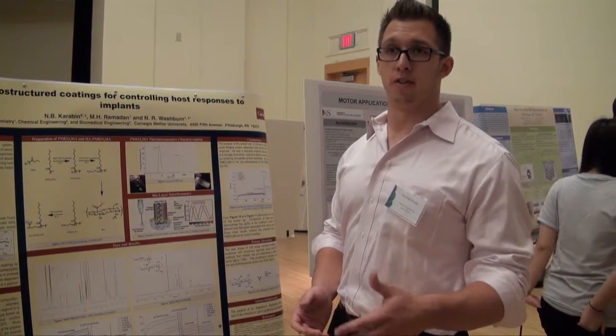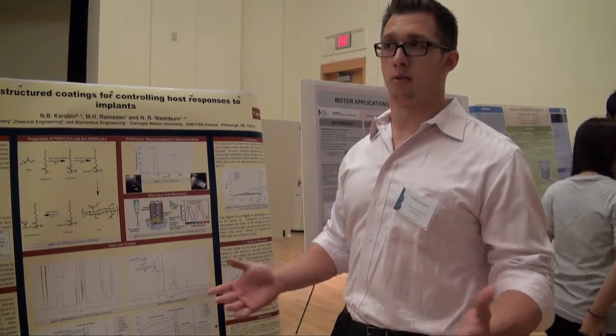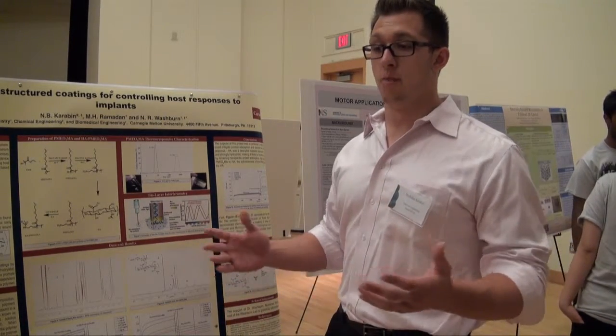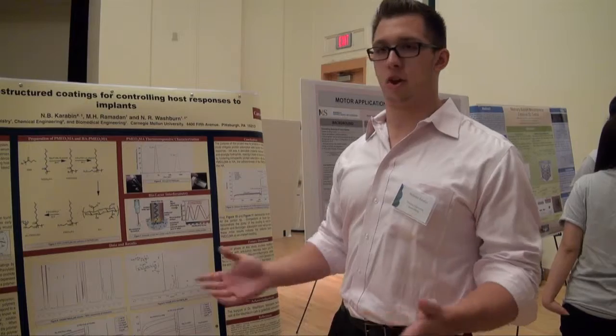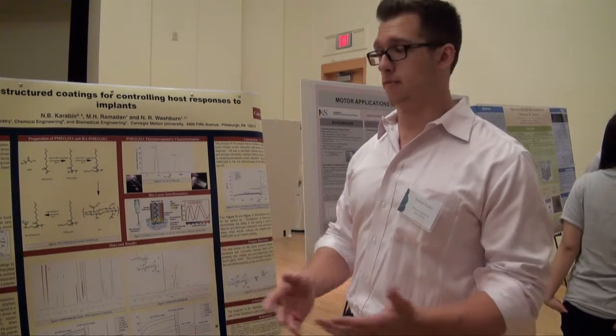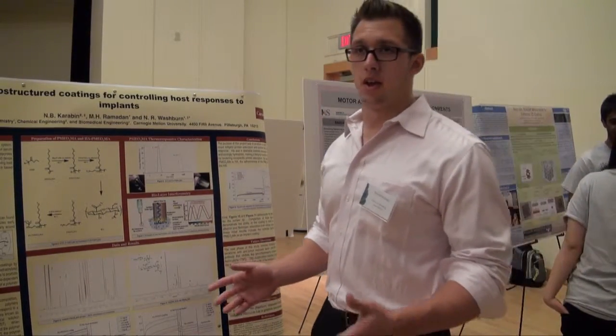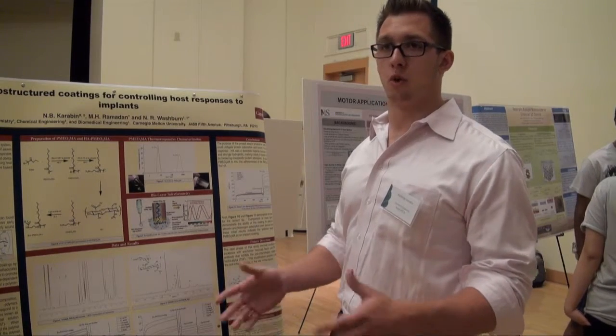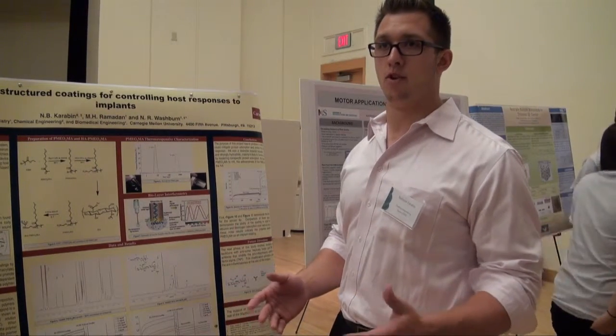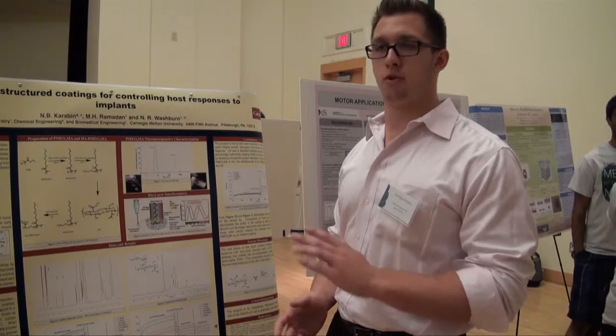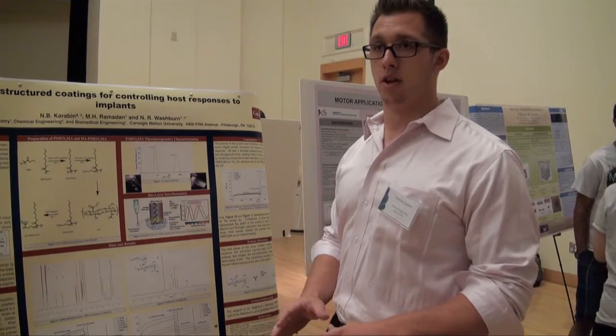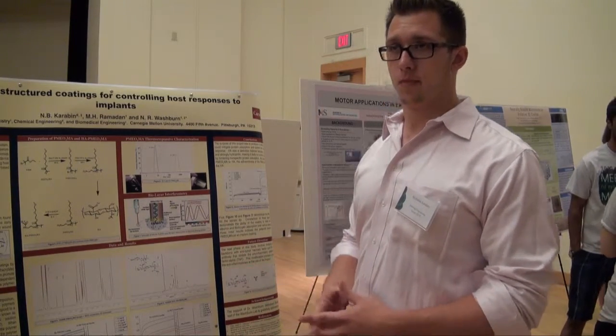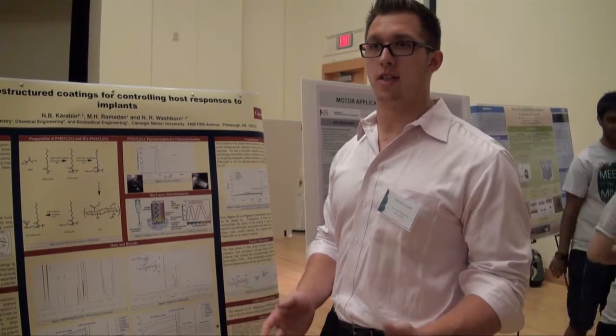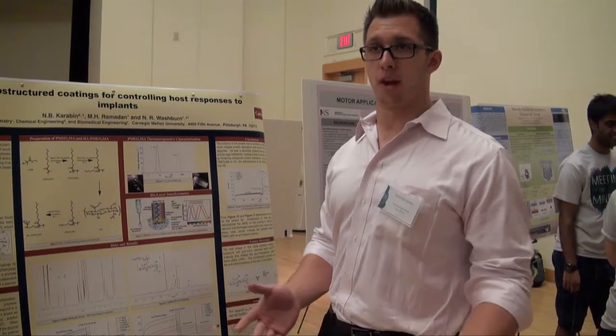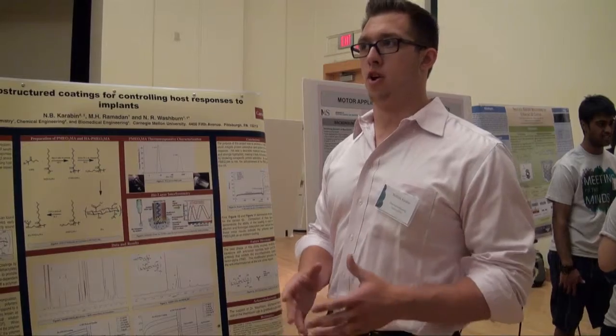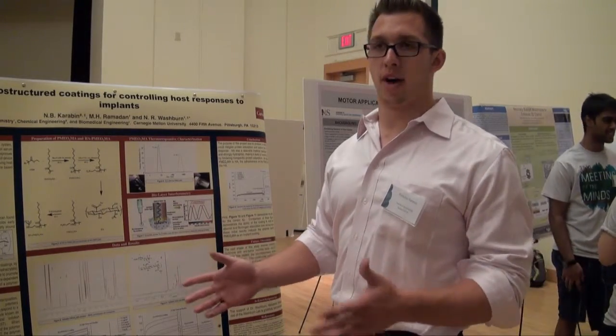When this occurs, the proteins eventually denature. The denaturation of the proteins causes an immune response that can range from chronic inflammation to device failure. So in order to prevent this, individuals are looking for a way to control the host response to that implant. One method is to use a hydrophilic coating on top of that implant that prevents protein adsorption. One current issue is that many of these polymers are synthetic polymers, and they don't always respond biocompatibly.